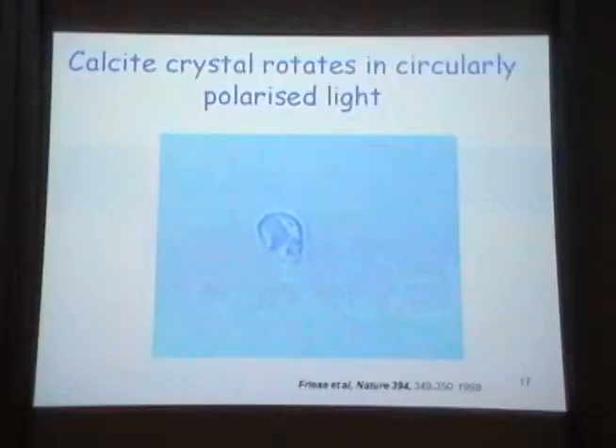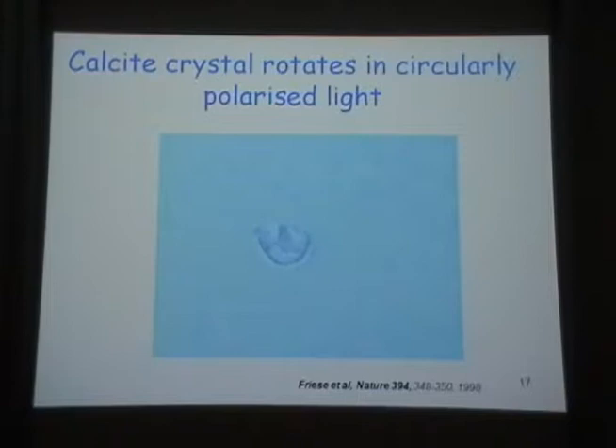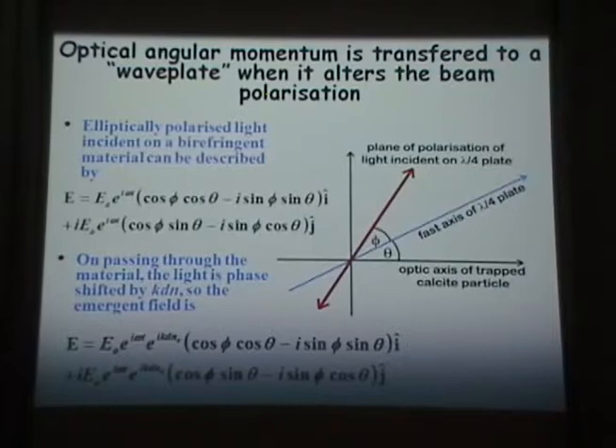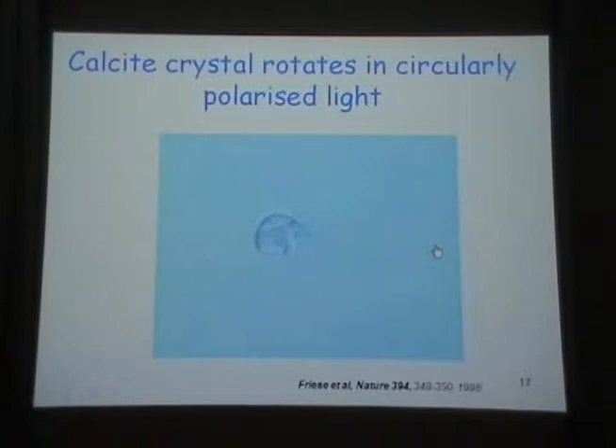Okay, and then again we have quite a large shard of crystal and we now put a lambda over 4 plate in this setup and I'm now transferring spin angular momentum to the plate. And it rotates nicely. It is quite large, about 9 microns in size, therefore it's not particularly strongly trapped in Z direction, because in Z direction the trapping is always much weaker, so it nudges the microscope slide, and therefore it jets back and forth in the beam. So it's not very nicely rotating. But when we change from left-handed to right-handed polarized light, the crystal changes the direction of rotation.